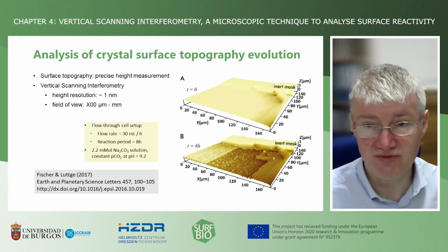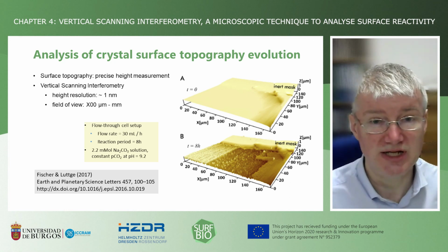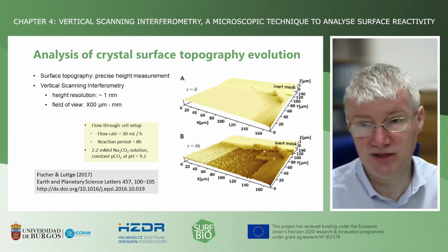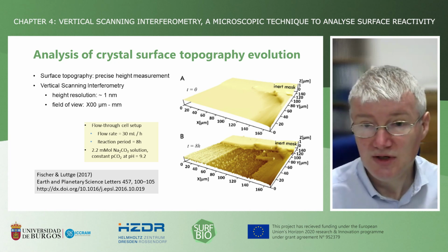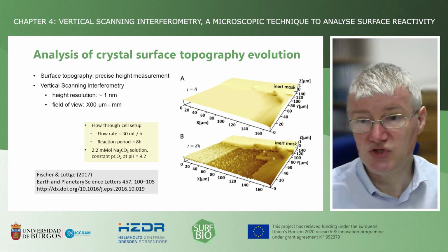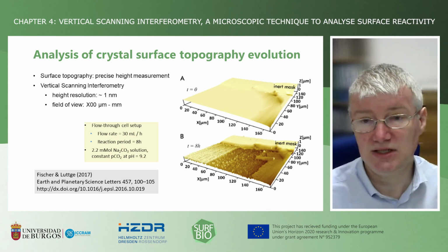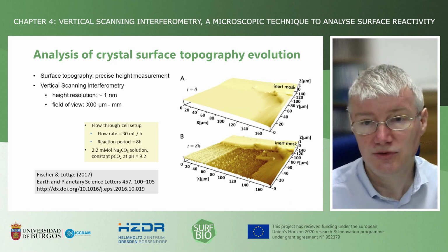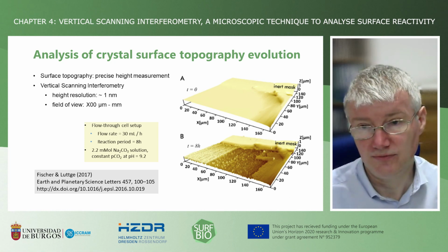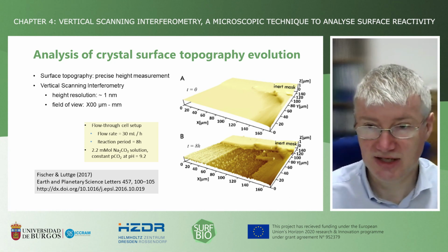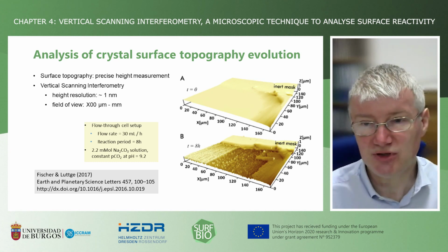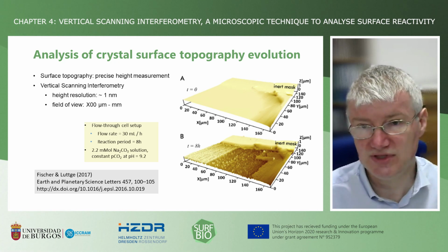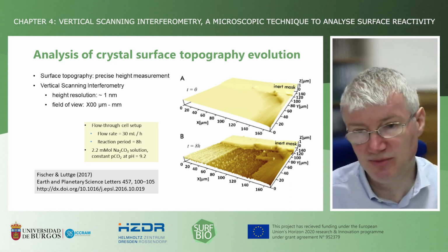In contrast to AFM, the field of view is usually much bigger, hundreds of microns up to millimeters, but with a very high precision in height. So this provides the opportunity to study large realistic surfaces during reactions. And with this example, again calcite, similar to the XY plot in the previous slide, we captured the evolution of surface topography with this method after a reaction time of about 8 hours.